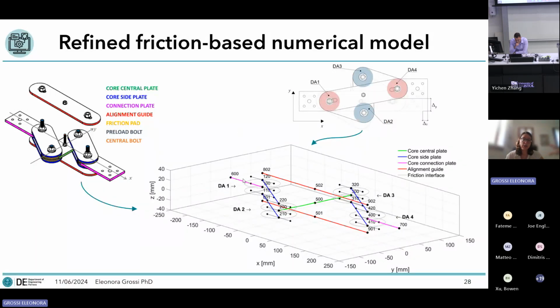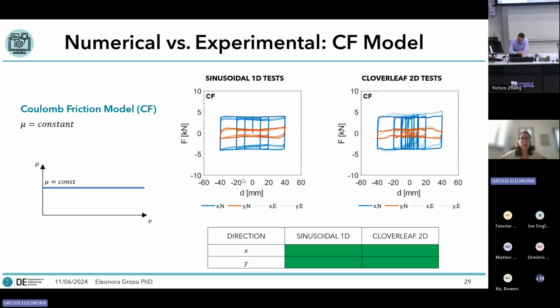At this point, I just needed to associate to my friction interface a constitutive friction law, and OpenSees allows me to associate different friction laws to the flat slider bearing element. First of all, I investigated the Coulomb friction model in which the friction coefficient is considered constant. You can see here also the comparison between the numerical and experimental test. The numerical tests are here with the bold continuous line, while the experimental tests are the dotted lines. You can see that already with this simple constitutive model, the matching is quite good, especially for the monodirectional test. While for the cloverleaf test, there is still a gap in here at the maximum displacement. However, overall, the comparison is really good.